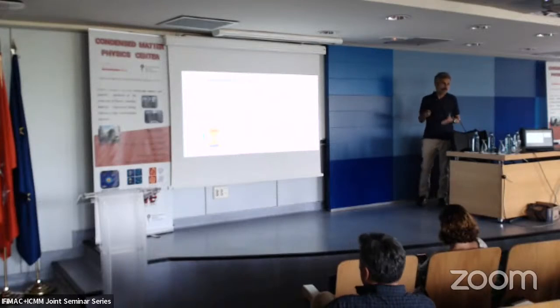The zero is when we make electrical contact with the sample. In this plot we are plotting the thermal conductance that we are observing. We are far away, more than 10 nanometers away, and we have no thermal conductance between the tip and the sample. We are separate enough. Okay, there is some radiation, but we are not seeing that because it is smaller. And then what we see is that around 7 nanometers, we find some conductance. This is before electrical contact.